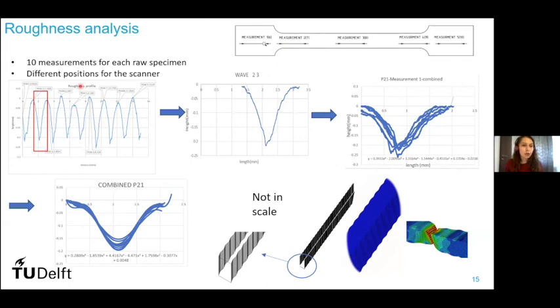First of all, I compared the roughness profile for every measurement, extracted all the waves, put them together and shifted them to 0 to get the 6-degree polynomial that best describes one measurement for a raw specimen. Moving on, I put together all the measurements and obtained the final 6-degree polynomial, like in this picture here, that best describes the roughness of one specimen, and did that for all the 18 raw specimens.